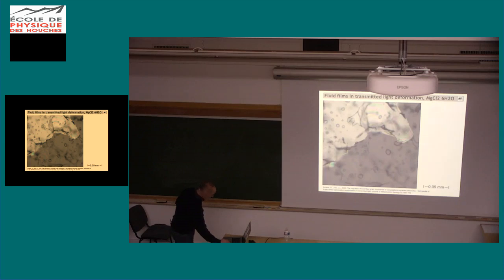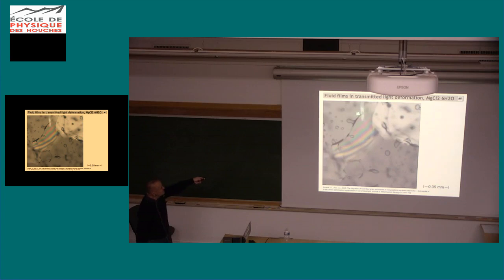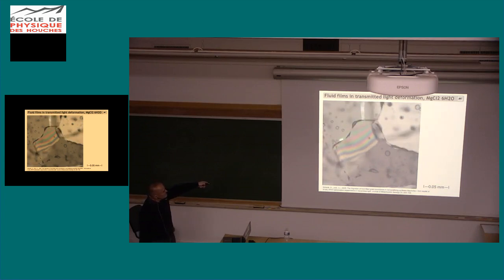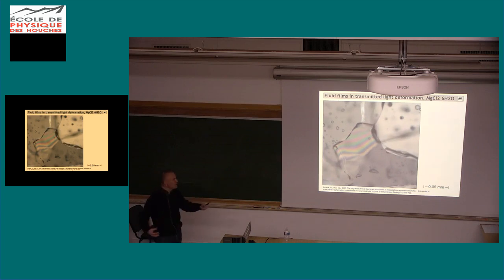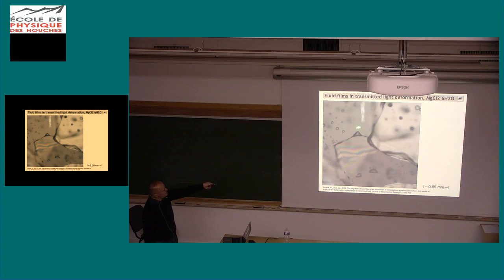And if this works, then I have a movie now. There you go. So you see this grain boundary, and here are the bubbles, the fluid inclusions, which play this game with the grain boundary. They go into the grain boundary, they come out of the grain boundary. This is a beautiful movie made by Oliver Schenk during his PhD. Here's a grain boundary dropping the fluid and leaving it behind.